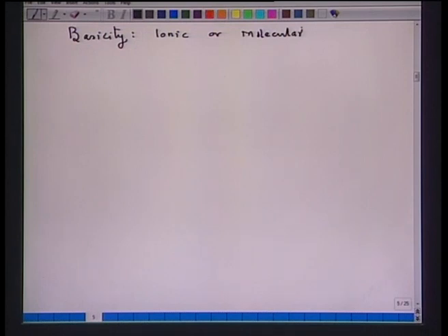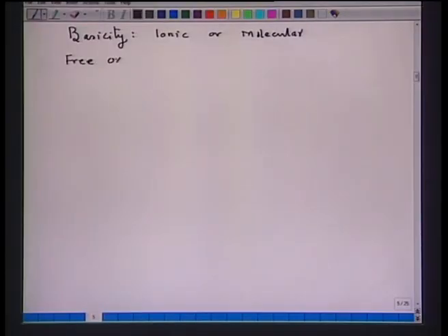Now from the ionic theory point of view, we know that most of the constituents in slag are oxides, some oxide donors, some oxide takers. So when basic oxides are added, oxygen ions will be available, and these oxygen ions break the tetrahedron. Any free oxygen ions available after satisfying the requirement of all acidic oxides is called the index of basicity. That means the presence of free oxygen ions is an index of basicity of a particular slag.